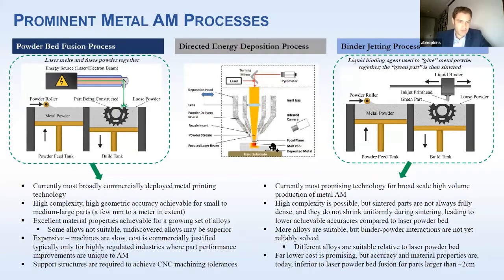So quick primer, laser powder bed fusion. You have a powder stage. It's not necessarily on the left, sometimes it's from above, but you distribute powder across the bed layer by layer. So you put down 50 micron powder layer. In other words, you drop the build tank as it's dropped by 50 microns, and you put powder on top. The thickness of the powder on the layer is not really 50 microns in this case, it's a couple hundred microns, sometimes 500. And then you scan a laser across the top in the outline or profile of the part you want to print. So if you wanted to print a pipe or an annular ring, you'd, roughly speaking, scan in a circle, and you'd melt.